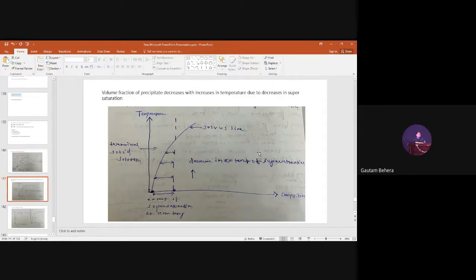So you can see here what is happening. You understand, this is your solvus line. This is the single phase and this is the two phase region. And if you remember, if this is the composition of your alloy, this much is the extent of supersaturation, from this one to this one. And you can see the extent of supersaturation is this much and this much and this much, with this being the temperature direction, right? So with increasing temperature, the extent of supersaturation is decreasing. So what is happening? The volume fraction of the precipitate is decreasing. That is the answer with increasing temperature.